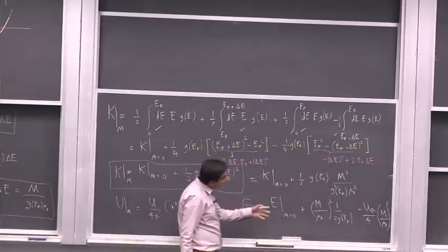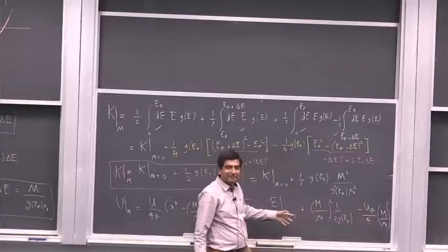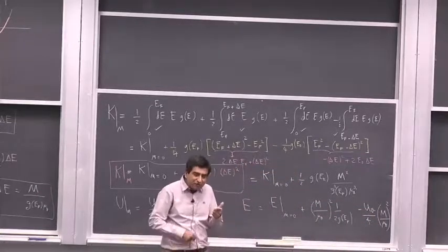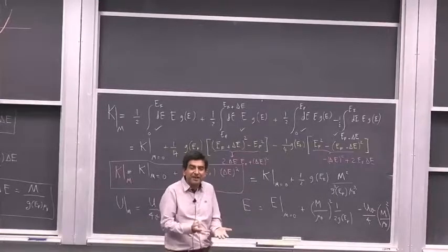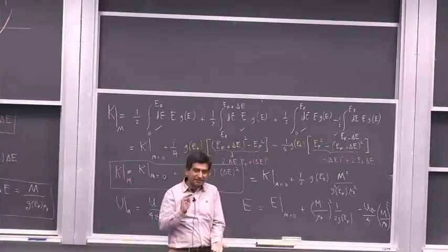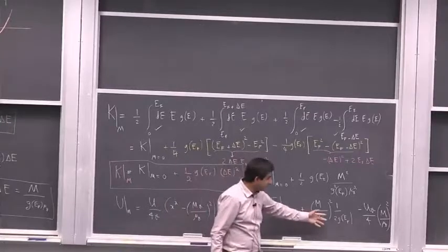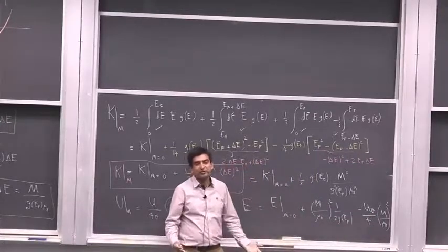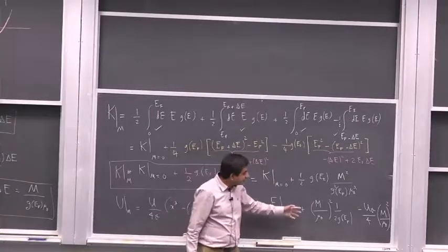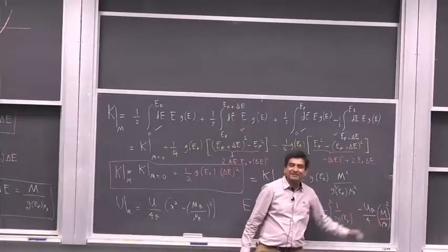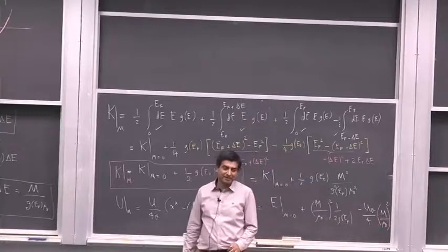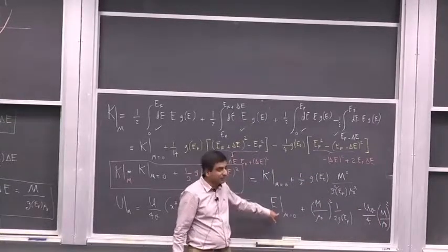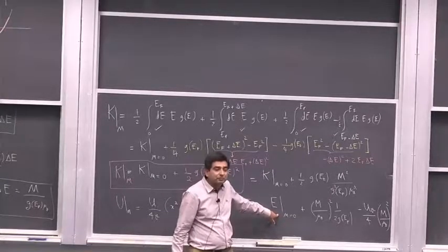So now let's look at this extra energy term. This is the extra energy term that comes out because of magnetization. If this term is higher in the presence of magnetization, which means that this term is positive, the overall energy is going up, and the sample would not like to spontaneously magnetize. However, if this term is negative, the sample would indeed like to magnetize, because that's going to lower the overall energy of the system from its native value.